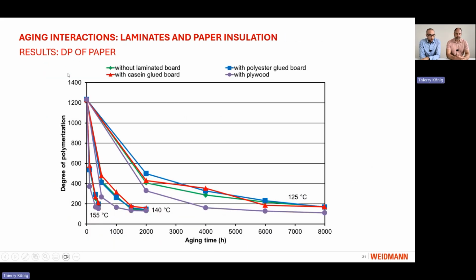Here are the results of the DP of the paper, which was aged together in green without any laminated material. In red, we can see the aging together with the casein laminated material. In blue, the one with polyester, and in purple, the one with laminated wood. And we can see the DP of the paper is already lower at the first measurement compared to aging together with all other materials. So the aging of the paper was faster when it was aged together with laminated wood, and that could be seen at all temperatures.